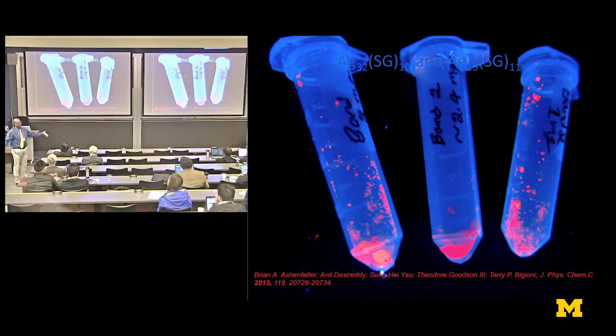Why? Okay. And here, everyone in this room could have done this experiment, right? Just by cutting that gel, and if you walked into a dark room with a lamp, you would have seen this yourself, an enormous fluorescence. In fact, we compared the fluorescence of silver particles to these clusters, and we said that the gold was about 5 orders of magnitude bigger. I mean, this must be 6 or 7 orders of magnitude bigger. And the question is why? So we tried to understand those properties.